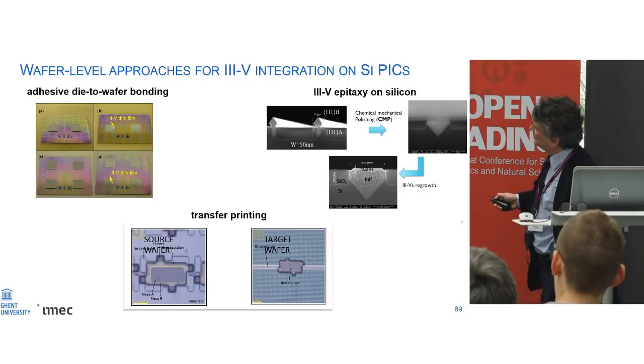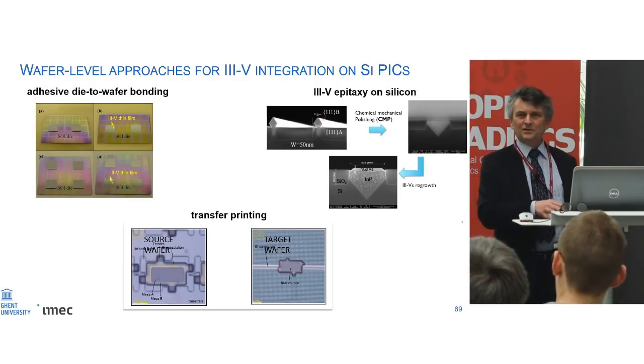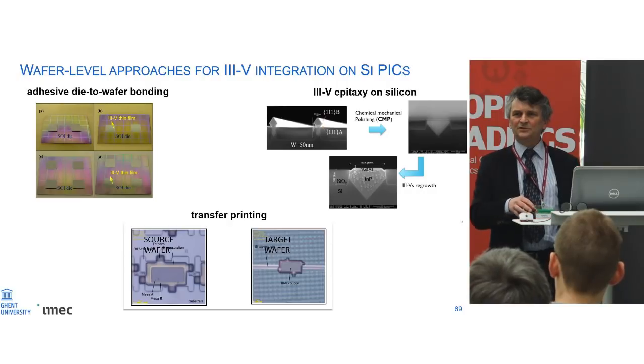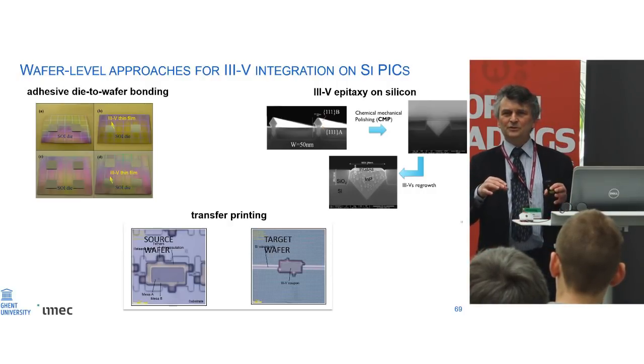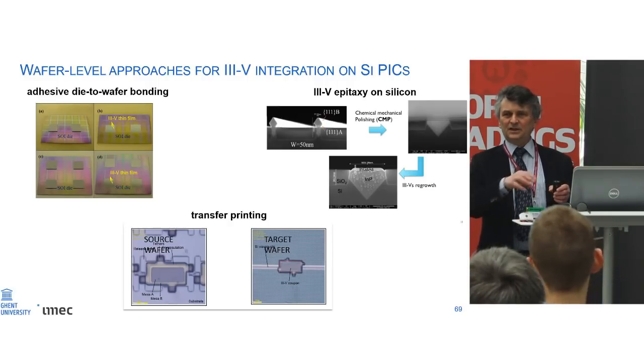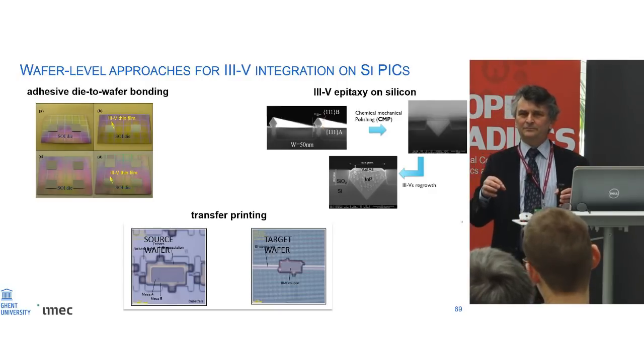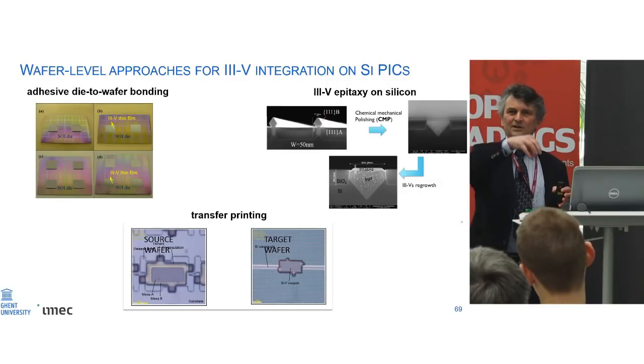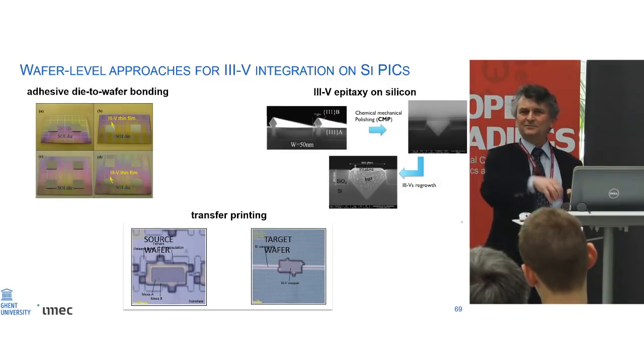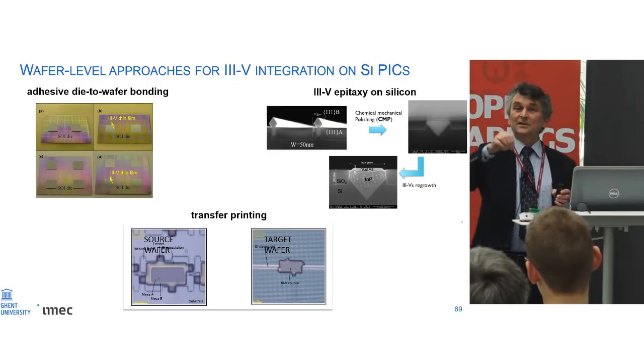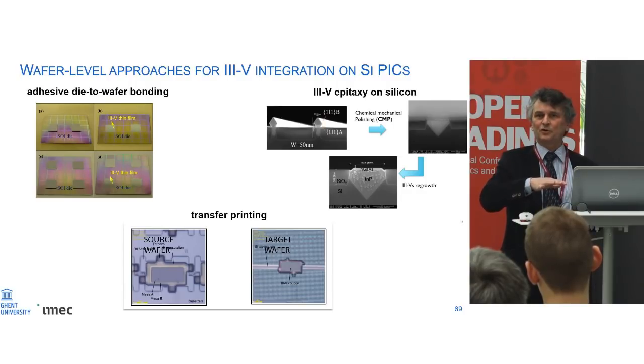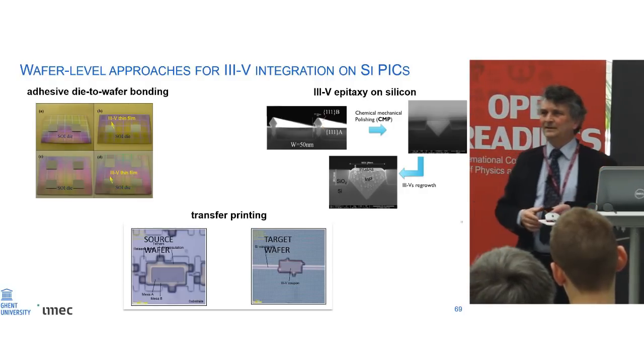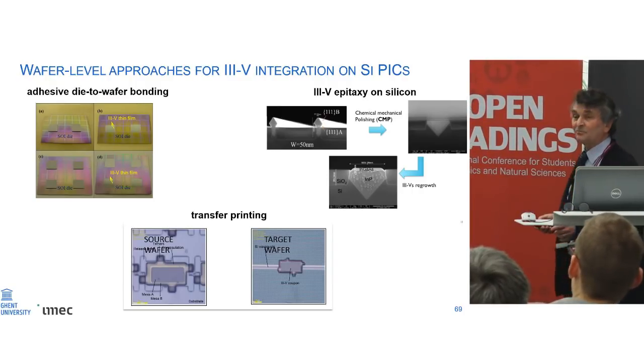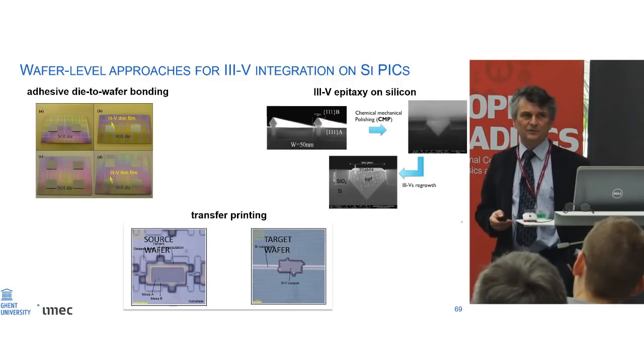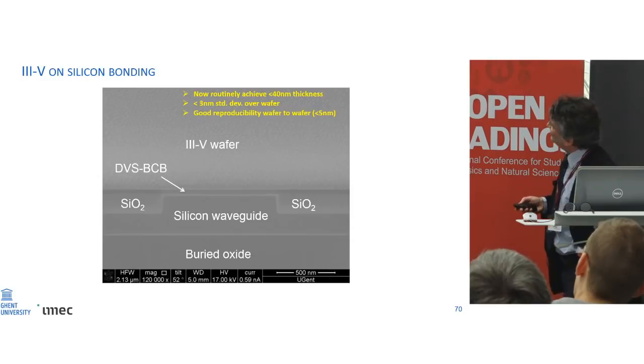I'll not go too much into the details, but here we basically first finish a laser onto its host III-V substrate until it's ready, and then with a few magical tricks, we make sure that laser device is detachable from its original host substrate. And then we come with a stamp, a rubber stamp, and we just pick up a laser from the III-V substrate and bring it to the silicon wafer. And in principle, that is a parallelizable process. You can, with a rubber stamp, pick up not one laser, but 1,000 lasers and transfer them to the silicon wafer. And likely, what I've described here, transfer printing, is probably the most scalable technique for integrating III-V on silicon. But I'll just give a few examples of what we have been doing.